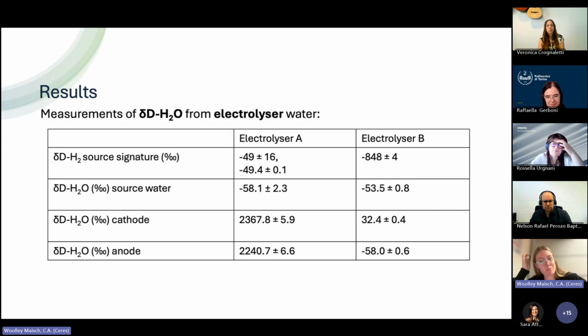This basically confirms our suspicion that the water has something to do with the source signature of the hydrogen. So we spoke to the operators of this electrolyzer, and they reuse the water over and over again. Once it gets down to a certain level, they top it up a little bit, but essentially as the electrolysis happens 24/7 or 24/5, the hydrogen is getting used up, and then the deuterium is left over, and we get more and more deuterium in the water, and then eventually that affects the source signature of the gas that is released. It makes sense when you think about it, but it's nice that we have this confirmation of that.